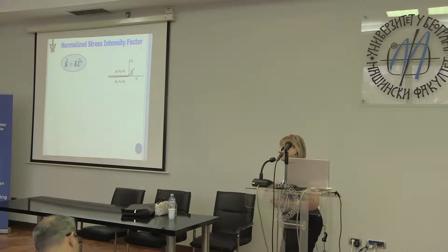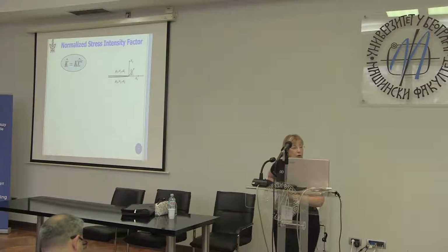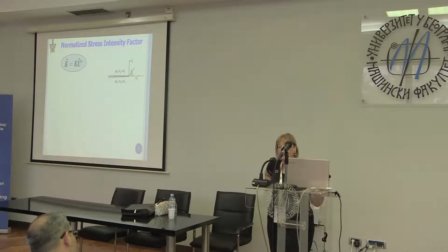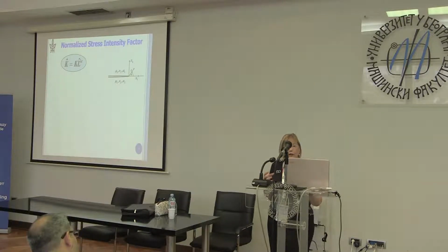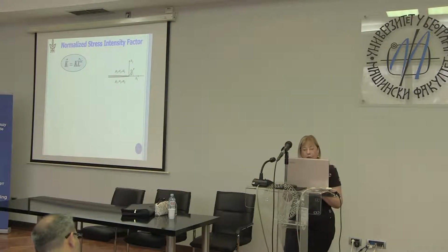So now people worried about this stress intensity factor that had these crazy units of L to the minus i epsilon. So you can normalize it with this factor L hat, which is arbitrary. You can choose it anything you like, but I have some advice. If you're carrying out a study in which you're looking at the effect of crack length, don't choose L as the crack length, because if the crack length is changing, then your units are changing. So pick L to be a meter, a centimeter, a millimeter, a micron. Pick it to be something, and then you can follow through, and you can vary your crack length. If you're going to carry out tests, we've used L as a free parameter in the test to fit the data and the criterion well, and I'll talk about that. So L hat is a free arbitrary parameter at this point.